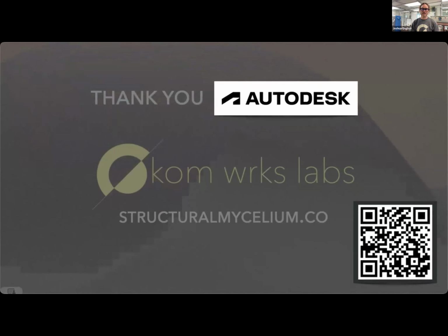We've made some concrete columns that are solid concrete, and then we've made some with one of our cylinders in the middle. And that initial anecdotal evidence just showed that we were able to displace about 25% of the concrete mass, and that we think we can actually get better using geometry in very interesting ways. That's John's actually expertise. I hope I'm answering that right, John.